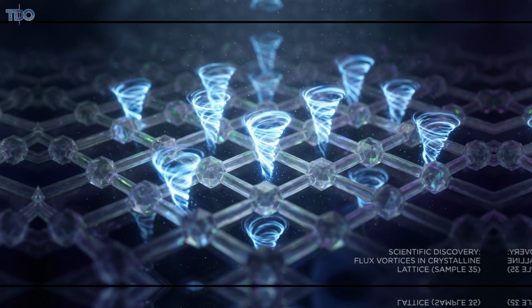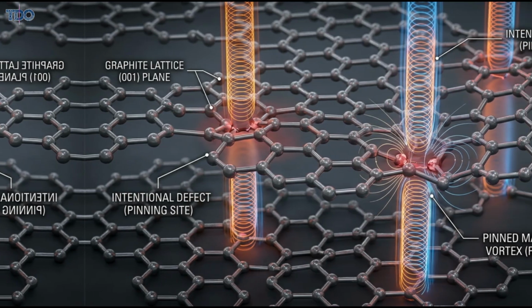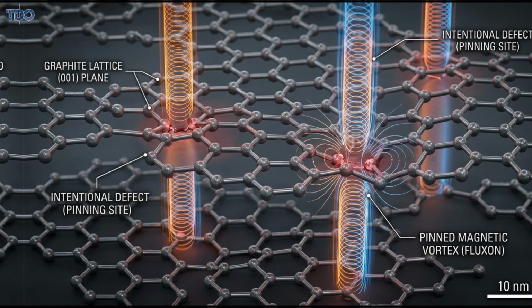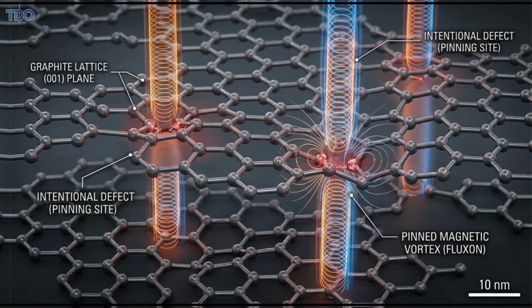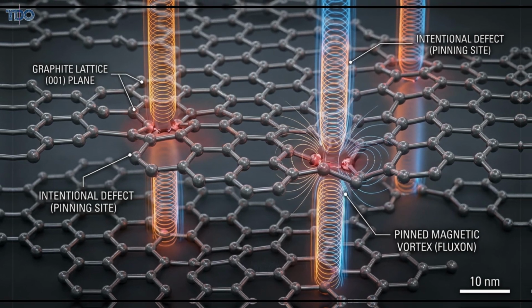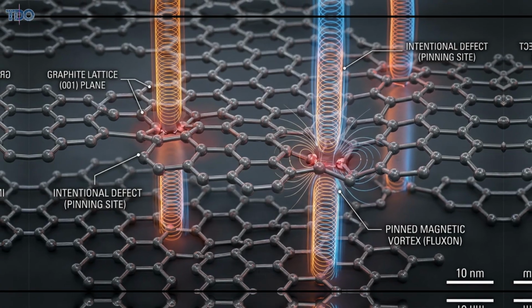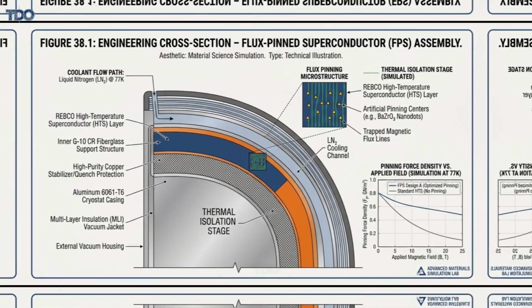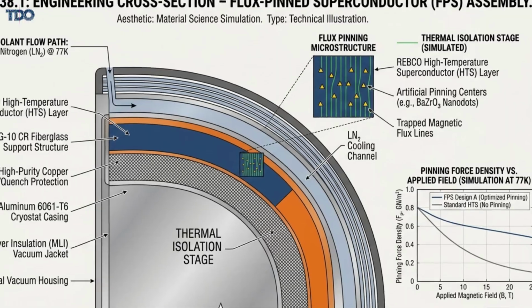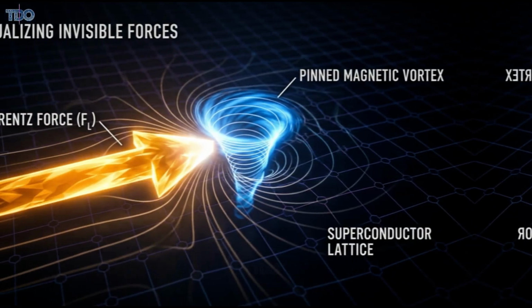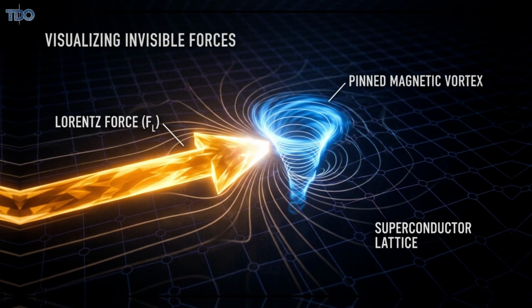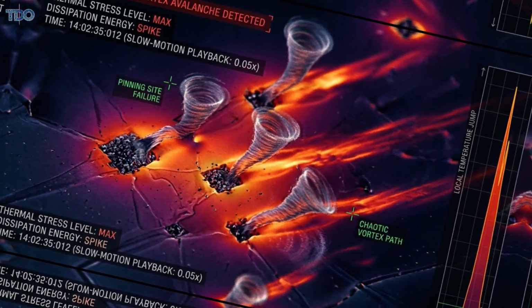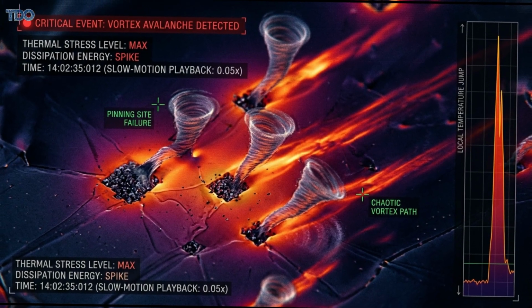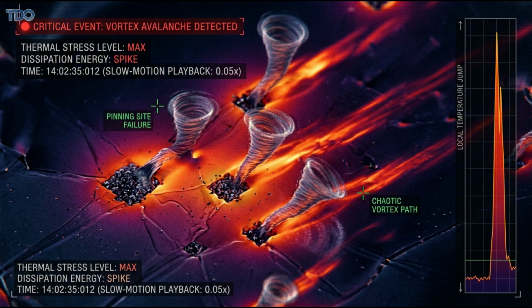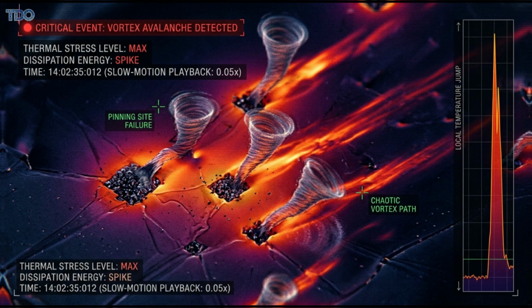To achieve a high critical current density, Jc, material scientists intentionally introduce microscopic defects into the material's crystal lattice to pin these vortices, preventing their movement, which would otherwise cause energy dissipation. However, this flux pinning is an engineering mitigation, not a circumvention of the underlying physics. The transported current exerts a Lorentz force on these pinned vortices. As the current increases, this force eventually becomes strong enough to rip the vortices free from their pinning sites, triggering a rapid transition of vortex motion, a sudden return of resistance, and a thermal quench.